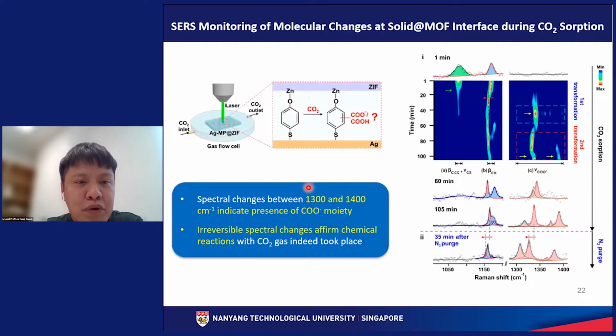So after which we perform in situ SERS monitoring of the molecular changes at the solid@MOF interface during CO2 absorption. Again, we use a gas flow cell that is made of quartz with gas inlet and outlet. So the main purpose here is to confirm the carboxylation reaction between carbon dioxide and our substrate, and where the carboxylate group is being formed. Okay, so this again is very similar to what we have seen earlier.